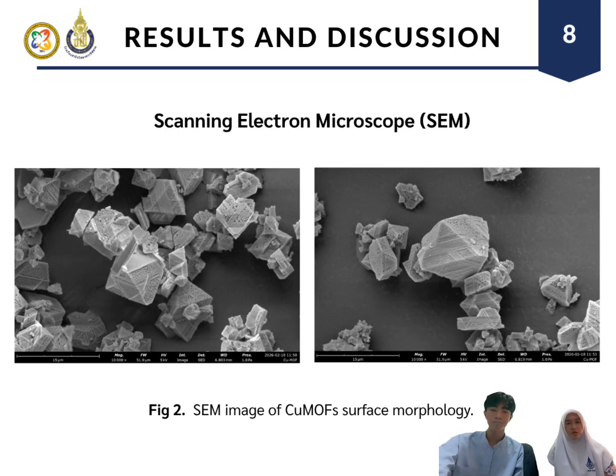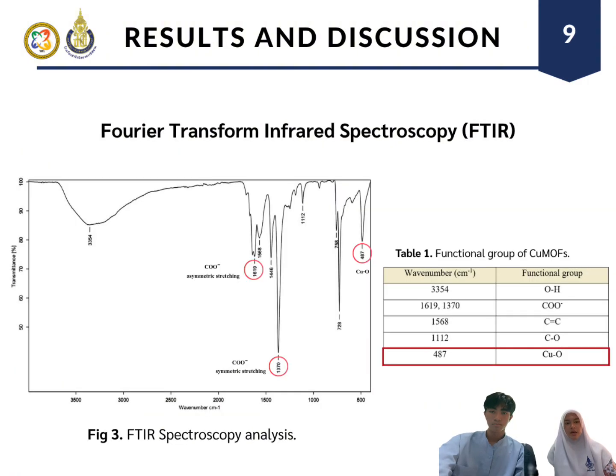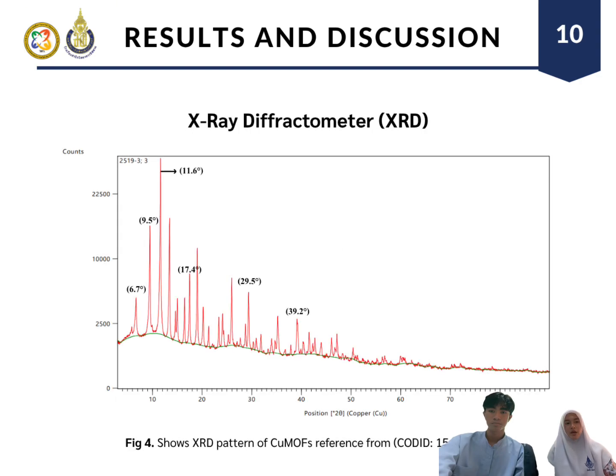This SEM image shows the morphological characteristics of copper MOF. The crystals exhibit a well-defined octahedral shape with sharp edges. The FTIR spectrum shows a peak at 487 per centimeter corresponding to the copper-oxygen bond, which confirms the formation of copper MOF. The XRD pattern shows several sharp peaks at 2 theta of 6.7, 9.5, 11.6, and 17.4 degrees, which match the characteristics of HKUST-1.